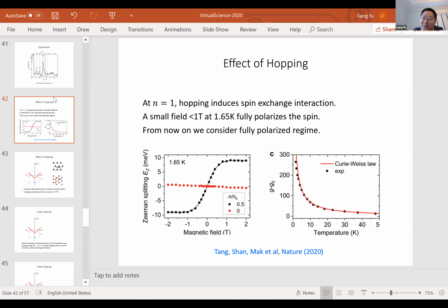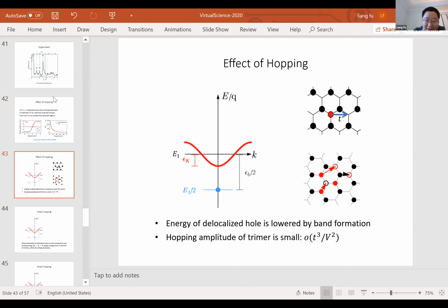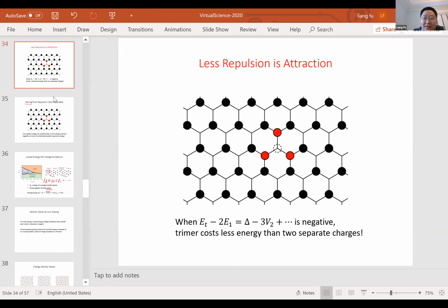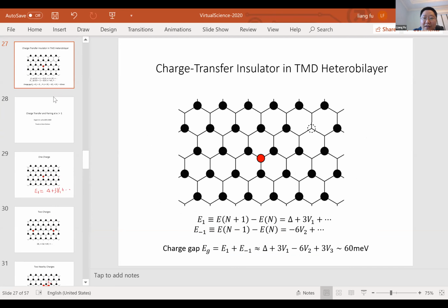That's actually an excellent question. I think it really depends. There are several exchange processes one needs to take into account. There could be a direct exchange, for example, if you look at, let me go back to the case of n equals 1. So you could have a direct exchange, where this charge hops to here and hops back. Or one can have a super exchange, for example, a charge hops to here, this charge hops to here, and this charge goes here. So it really depends on the relative magnitude of these different exchange processes. This is something that we are still studying.